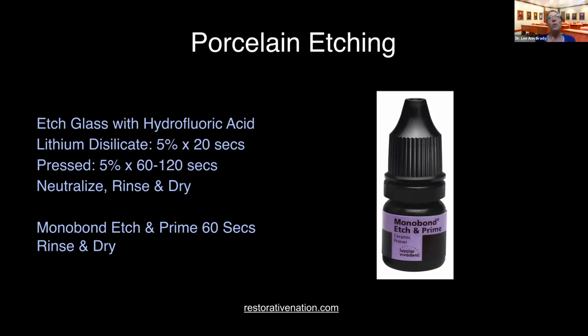And so I know when I'm doing an Emax-based restoration, I'm going to try it in, adjust my contacts, adjust my occlusion, polish, whatever your protocol is. And then I'm going to do a 60-second application of Monobond Etch and Prime. I'm now etching it. I'm cleaning it, so I don't have to use IvoClean in this situation. And I'm also priming it, so I don't have to use my Monobond Plus. One step, 60 seconds, one bottle. And I get to do all three of those things, and there's no risk of over etching.